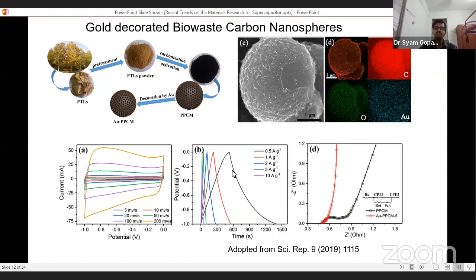And what we can observe is that it's reaching around 300 to 400. And even in this Nyquist plot, when we observe this gold decorated material, if this particular shift is towards the y-axis, we usually say that the capacitive property of the material is increasing. That means the resistive nature of this particular material is decreasing. So this is one of the recent researches where they just added some gold precursor during the carbonization technique, and they synthesized this gold decorated carbon nanosphere, which has given very improved results. Similar sorts of researches are going on.